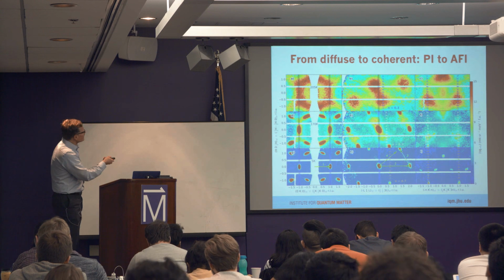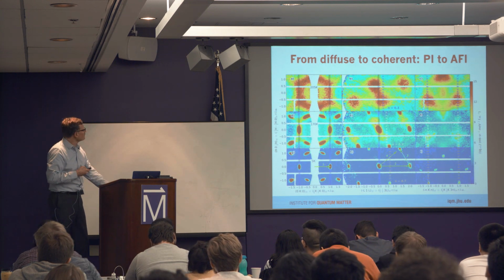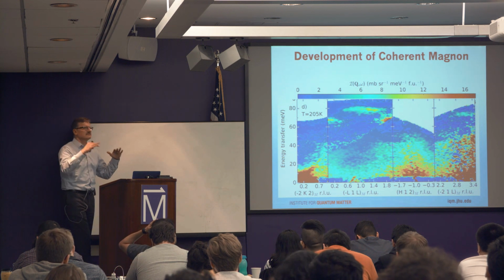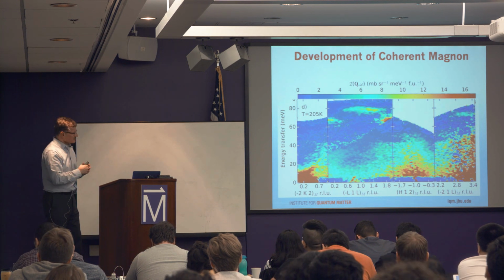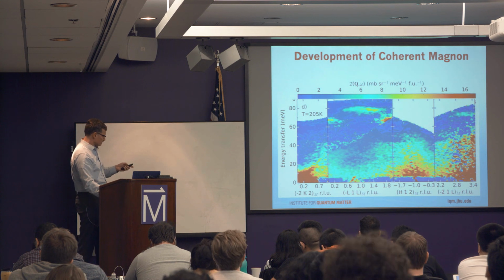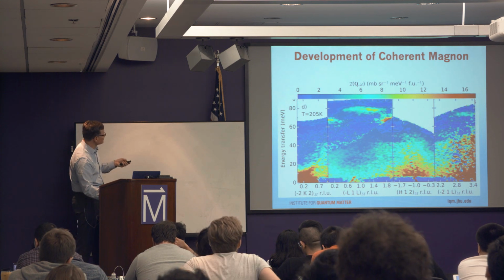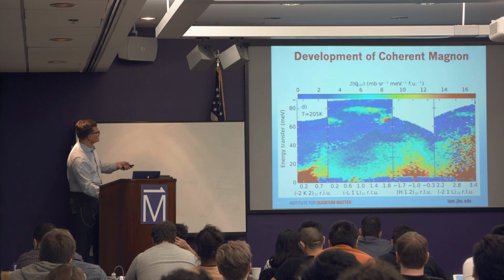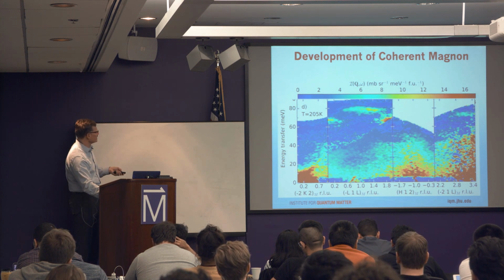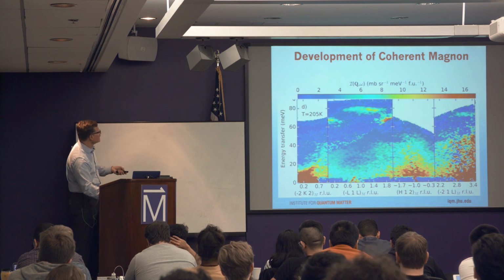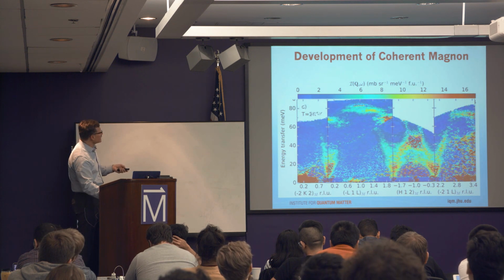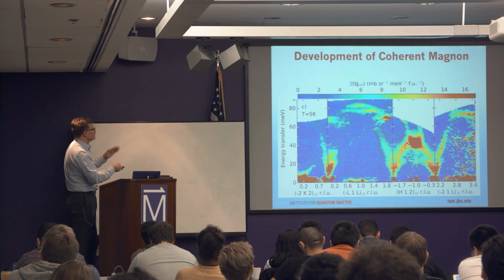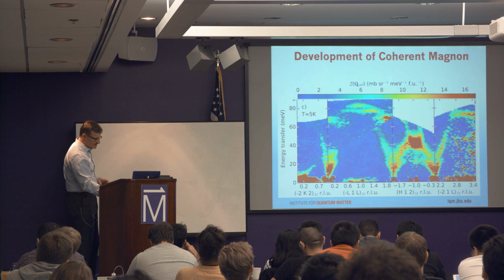And so you can ask, why is this phase transition occurring? To answer that, we have to analyze the magnetic excitations in the ordered magnetic state. So I want to show you what happens to the inelastic scattering, now shown as a function of energy and momentum transfer. This is what it looks like in the paramagnetic state, very close to the phase transition: really broad and dull-looking features. Then we cool into the ordered state, and we have a pretty dramatic development of spin waves out of this morass.